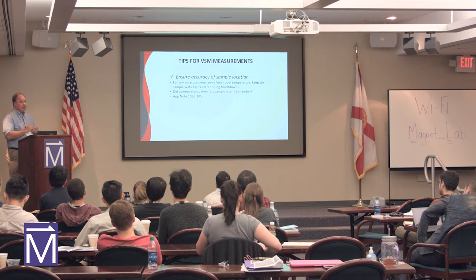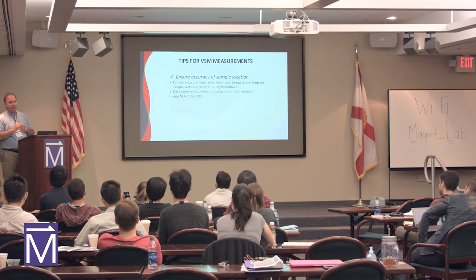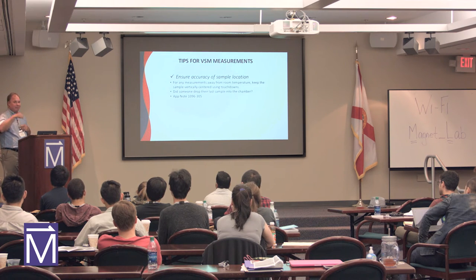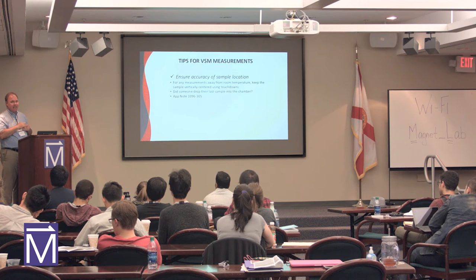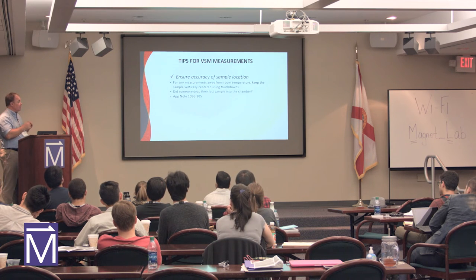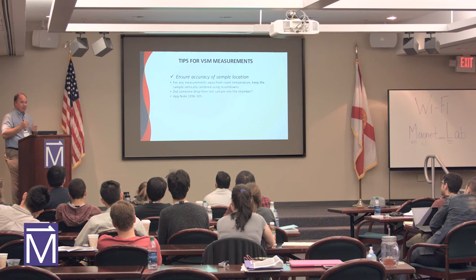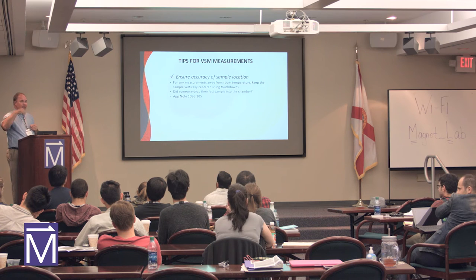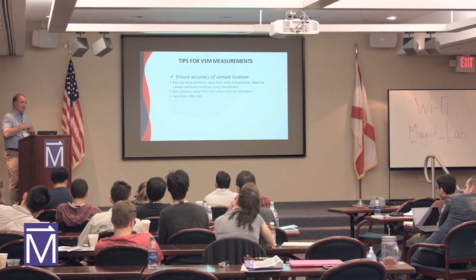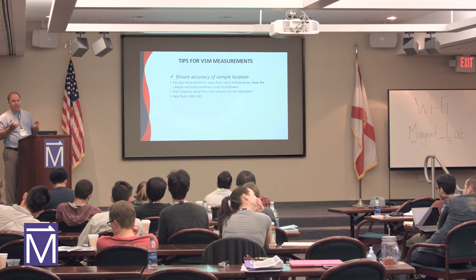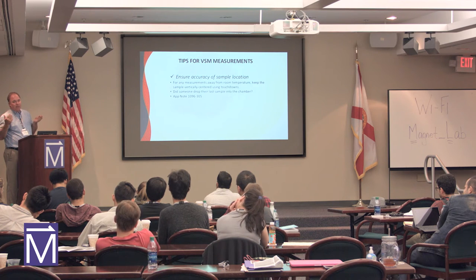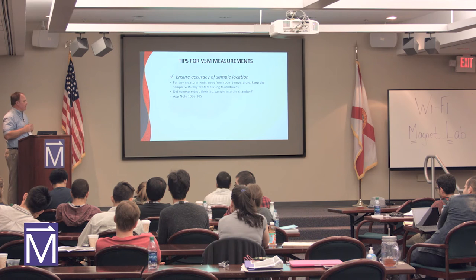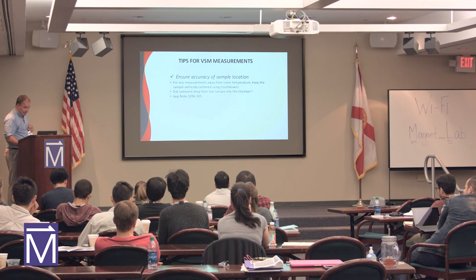A common thing is that our service guys will go in and find that somebody dropped the sample. Oh, the VSM doesn't work. Some people make a measurement, the sample falls off into the bottom, it does the touchdown, and then things are off spatially because it's hitting the last guy's sample. I was asking the service manager what the common thing is. He said this is very common because people drop things in there, and then they leave, and they don't tell the next person, and then people are scratching their heads while the instrument doesn't work. So if you drop something in, tell somebody. Just don't leave it in the sample space. If you tell somebody, people are pretty nice. Otherwise, you're going to have to go fishing, but it's better to do that than have bad data. And there are a couple of application notes on these things.